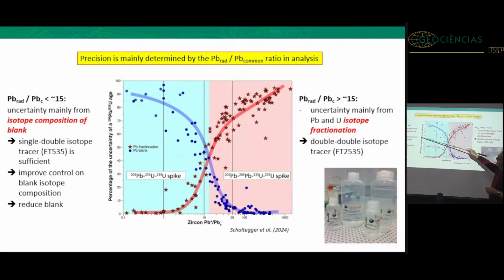And when you look at the percentage of the uncertainty of a 206/238 age, here you would have one factor taking all the uncertainty you produce. Here you would have two factors equally participating in the uncertainty you produce. So in the blue area, the main reason for the uncertainty is the lead blank. This is an area where the isotope composition of the lead blank and the low radiogenic to common ratio are making the lead blank the most important source of uncertainty.